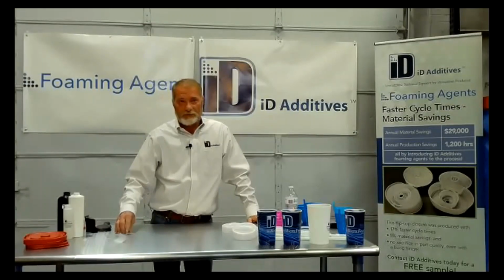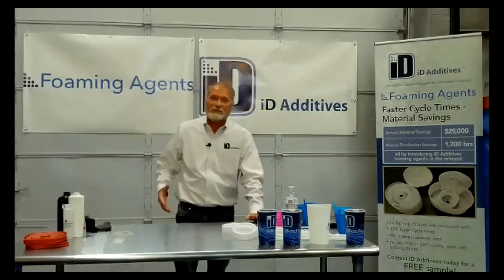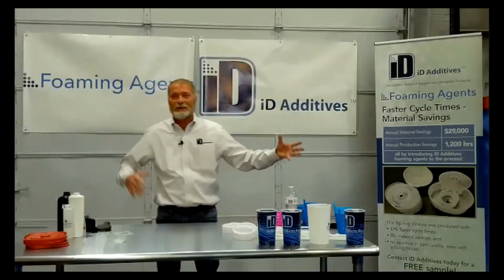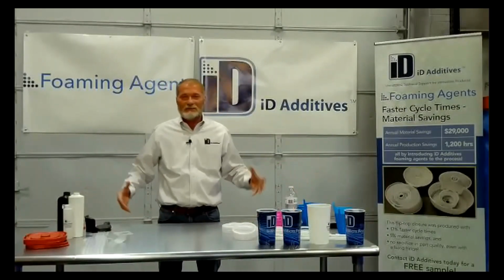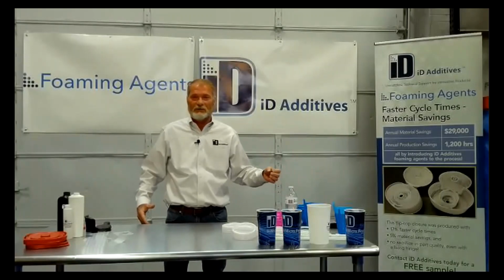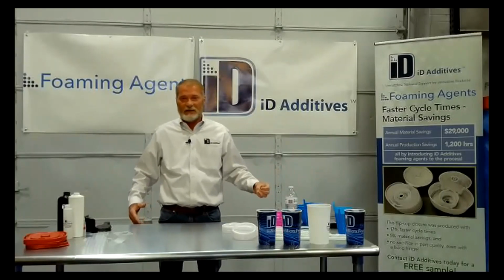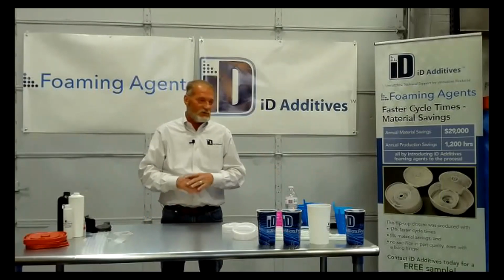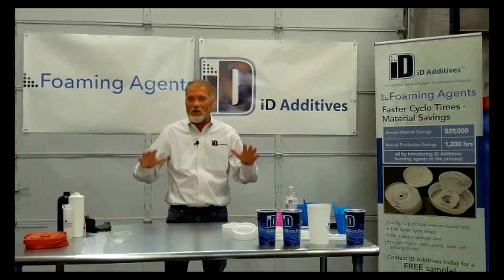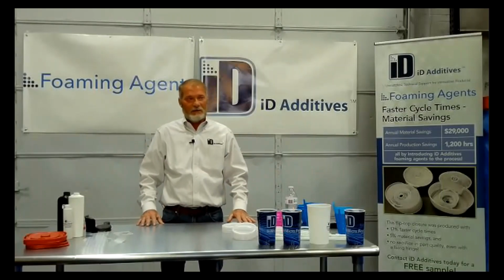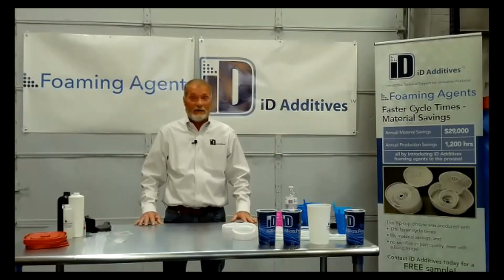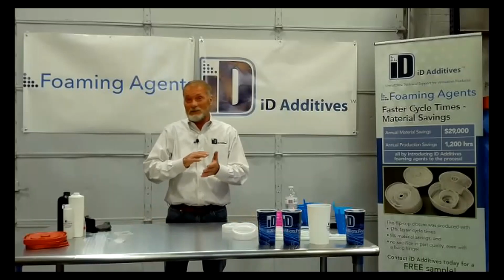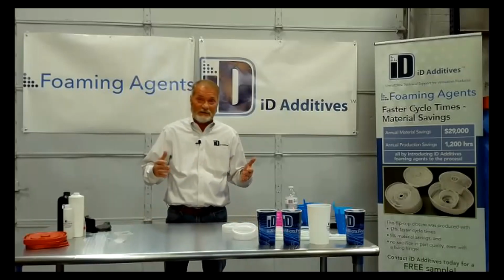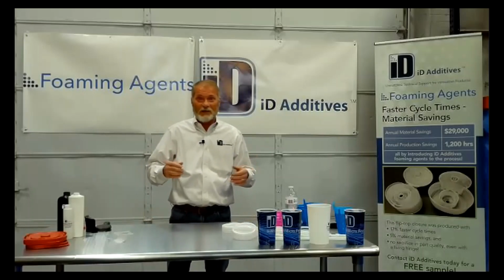One of the last few questions: does foam help or hurt paintability of parts or even welding? Sure. So when you're talking about foaming agents, you're talking about exothermics, endothermics. Exothermics, whether it's injection molded or extrusion, they have to degas. And exothermics are notorious for slow degassing. I've molded parts that took 2 weeks before they could paint them, or before they could put a simple label on it. Because if they didn't, a day or two later, it'll bubble up.